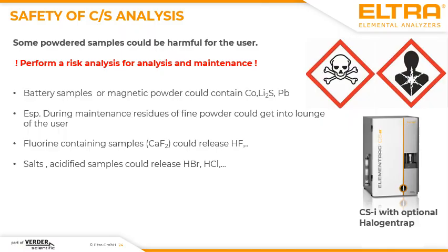When you have an analyzer like the Elementrac CS-i and you have to make sure that, for example, halogens are absorbed, which can damage the analyzer, then you have to apply a halogen trap. And with this kind of trap, you are sure that no halogens are getting into the detection part of the analyzer and destroy the analyzer.